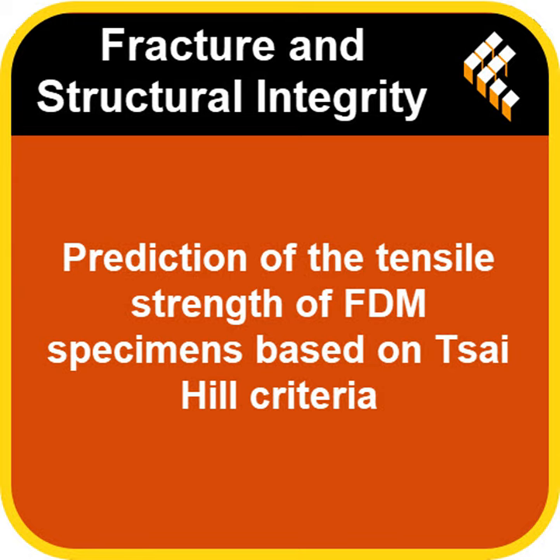For the 45-degree parts that did have the contour, the Tsai Hill model predicted a tensile strength of about 53 megapascals, 52.95 to be precise, and what they actually measured in the lab was 51.1 megapascals. That's pretty close. What's the error? Only about a 3.5% difference, which is quite good in material science terms. Okay, not bad at all. Yeah. What about without the contour?